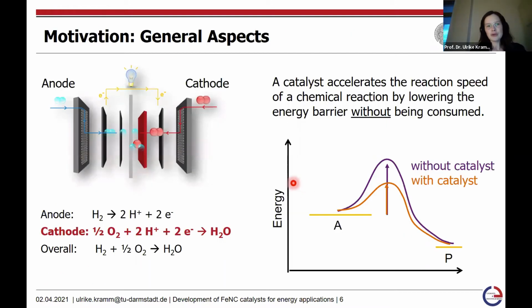In a hydrogen fuel cell, this is basically an electrochemical device. We have on the anodic side the hydrogen oxidation reaction taking place, and on the cathodic side we have the oxygen reduction reaction taking place. Both reactions require catalysts, and the state-of-the-art material for these reactions are platinum-type catalyst materials.